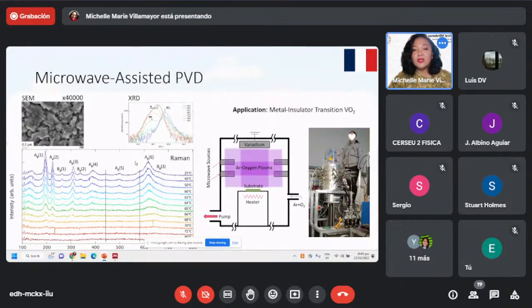So for the Raman response, we saw that at low temperature, the material gives off a signature Raman peak, which is insulating. However, at high temperature, or beyond the transition temperature, we have a flat response, which means that the material is metallic. For Raman, it behaves when the vibration of the electrons are excited, and if the material is insulating, it will have these signature peaks. However, if it's metallic, it will have a flat response. And we did this by heating up the material slowly, and we also measured the response after we cooled it down, and it did indeed go back to this 25 degrees Celsius signature.